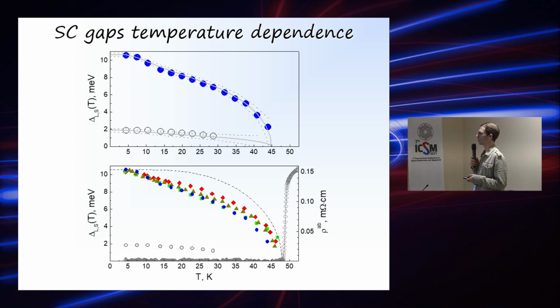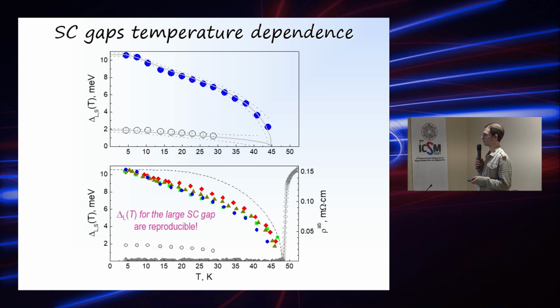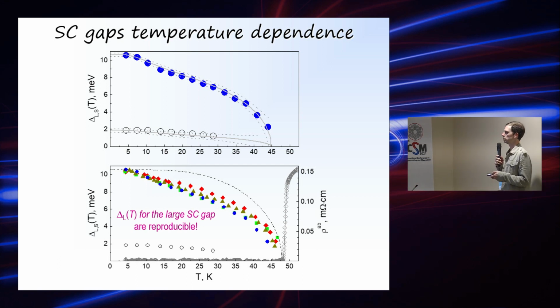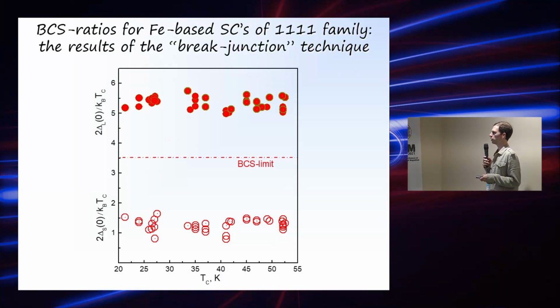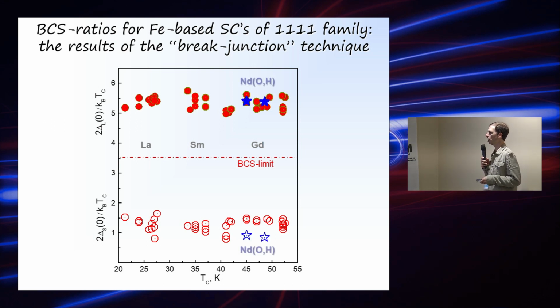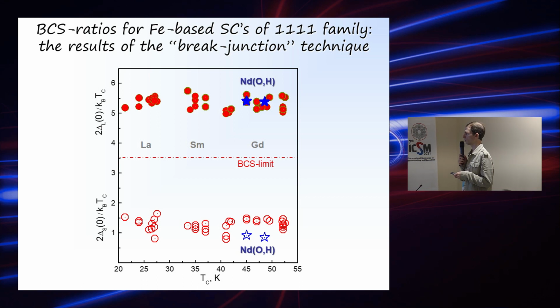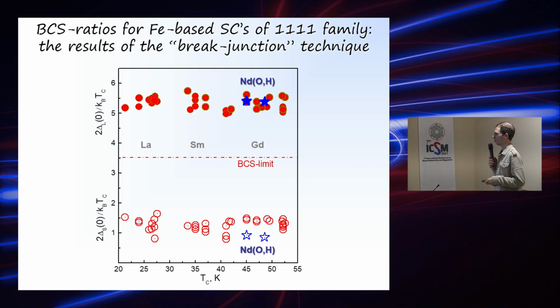And I'm finishing with the data of the characteristic ratio. You could see some of our old data by the break junction technique for other 1111 compounds, for the large gap and for the small gap. And new points are the stars for the neodymium 1111 with hydrogen substitution. And you can see that it nicely fits all this data.